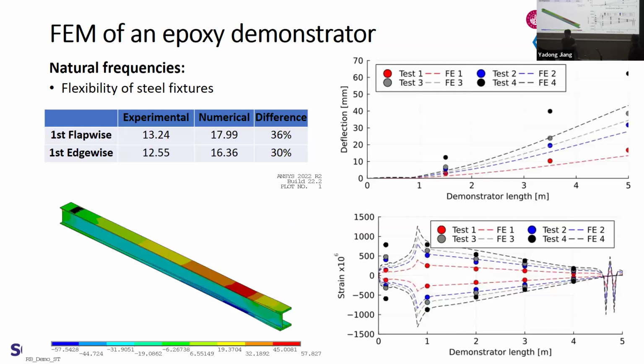When we compare the numerical model's predicted natural frequency, we see a difference of roughly 30% to 36%. And we think this difference was due to the flexibility of the supporting structures. When you are trying to hit this demonstrator, the support will actually move a little bit, and this small movement will introduce some error in the natural frequency test. We also observed some root rotation during the static test, which supports our conclusion.